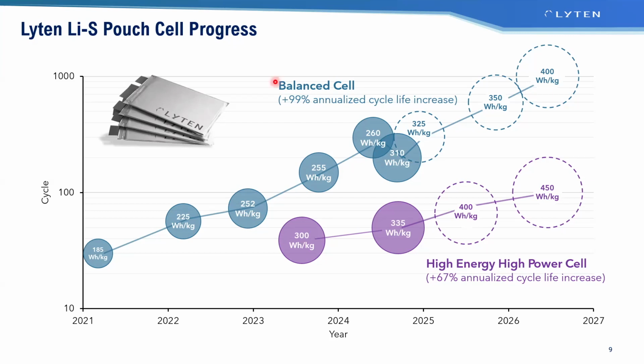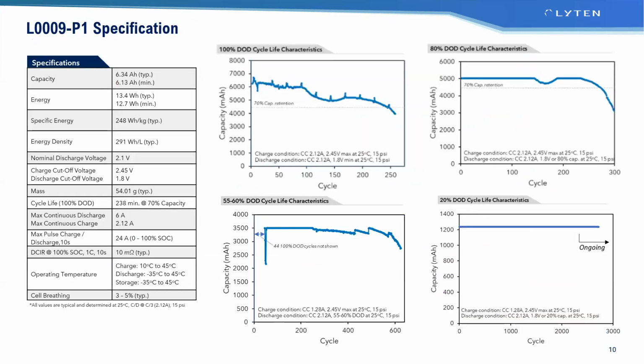And the other thing you should look at is that the traditional lithium ion improvement over time has been something like 4% per year of capacity increase. That is over time what lithium ion has done. We've been doing somewhat better than that. We're about 12% per year in energy density increase. On an R&D standpoint, it's a lot of work, but still, we make actual practical cells. We're actually cycling them and making progress.